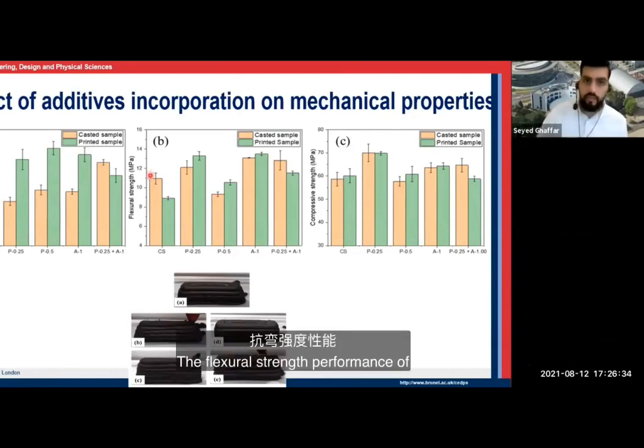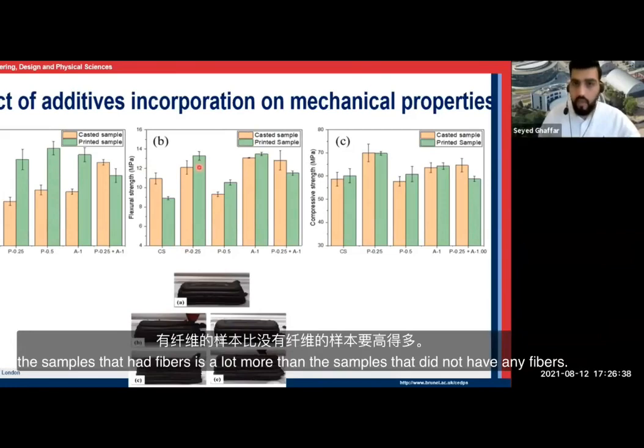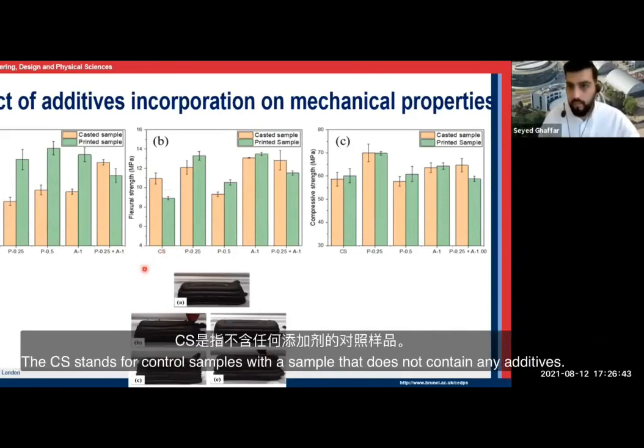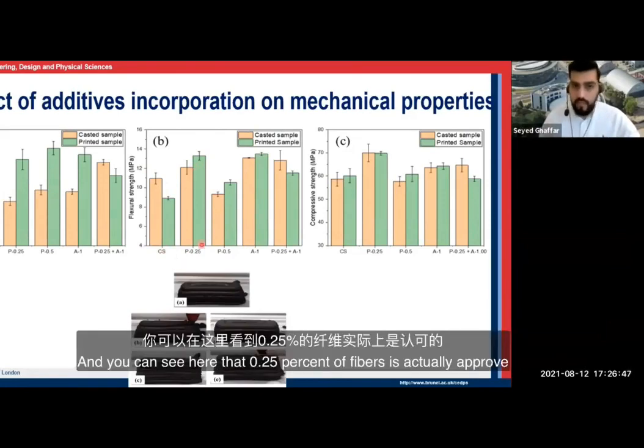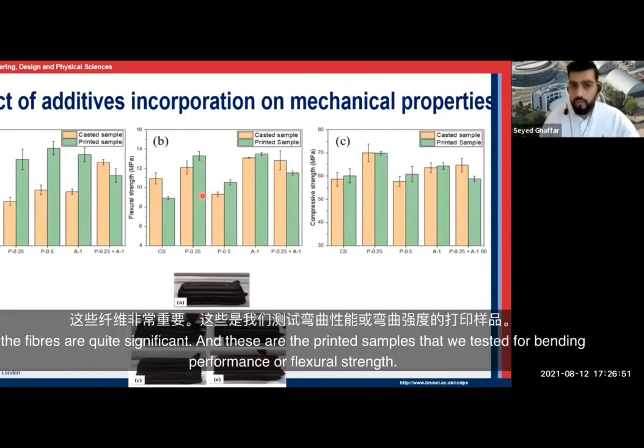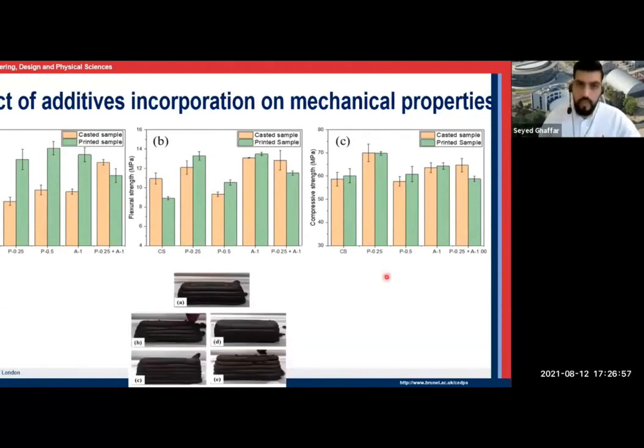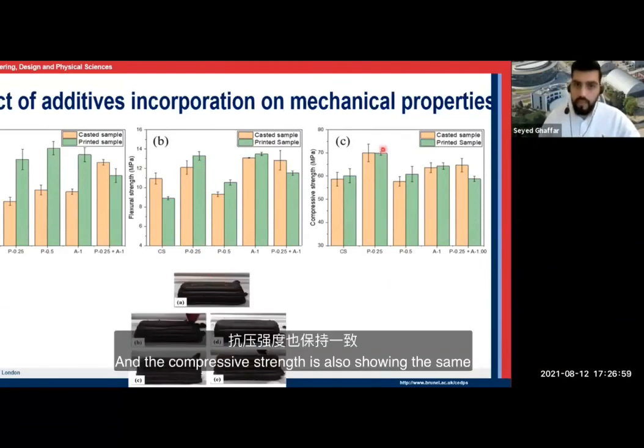The flexural strength performance of the samples that have fibers is a lot more than the samples that did not have any fibers. The CS stands for control sample, so the sample that does not contain any additive. And you can see here that 0.25% of fibers has actually improved the flexural strength quite significantly. And these are the printed samples that we tested for bending performance and flexural strength. And the compressive strength results are showing the same trend. So very encouraging results overall.